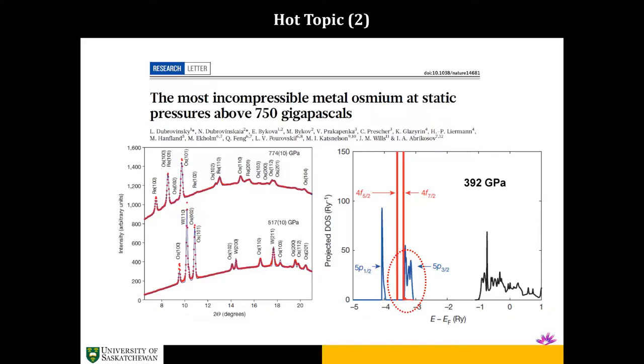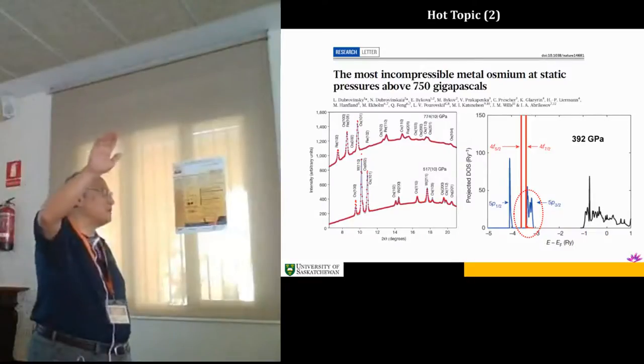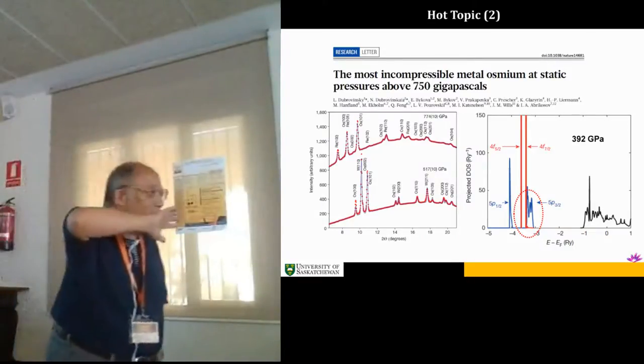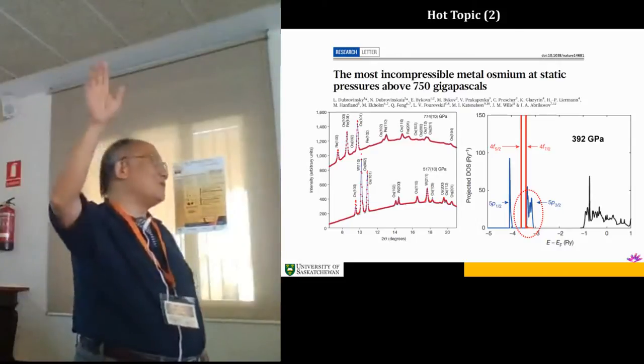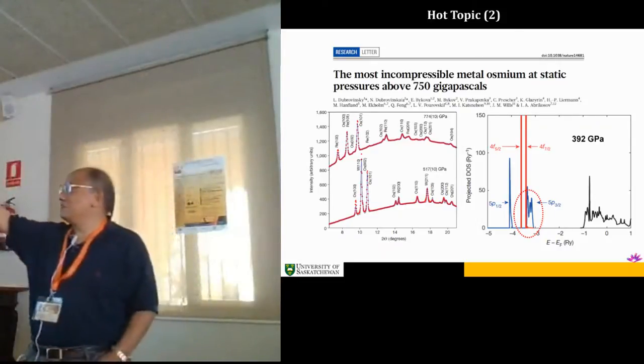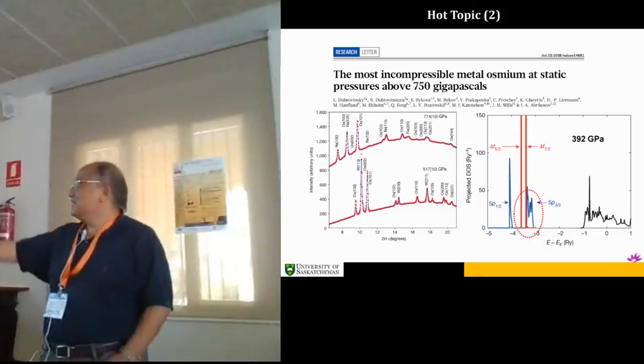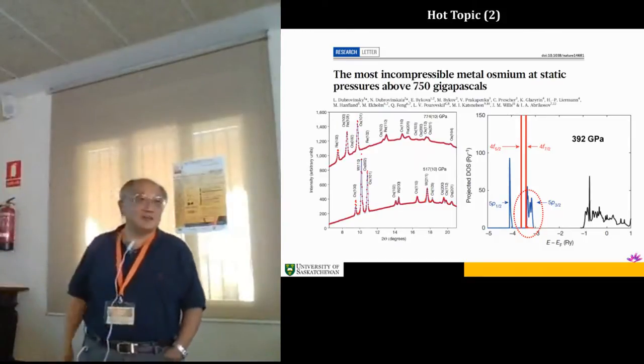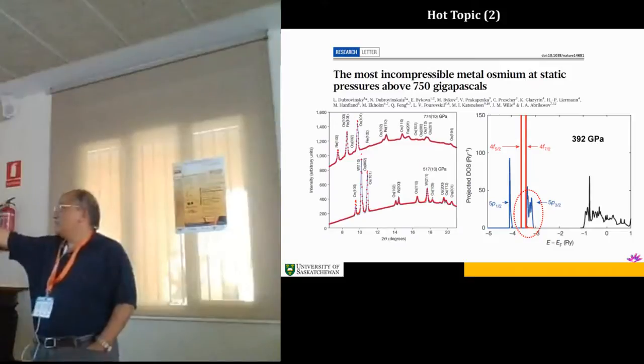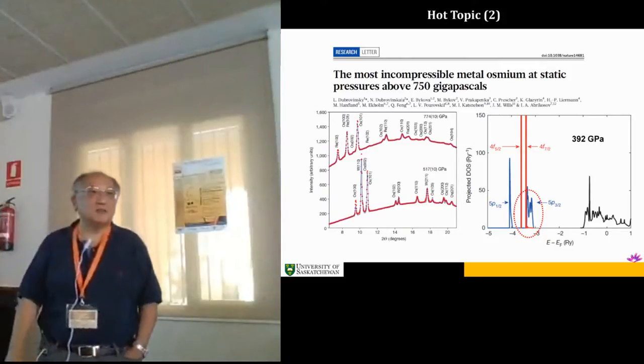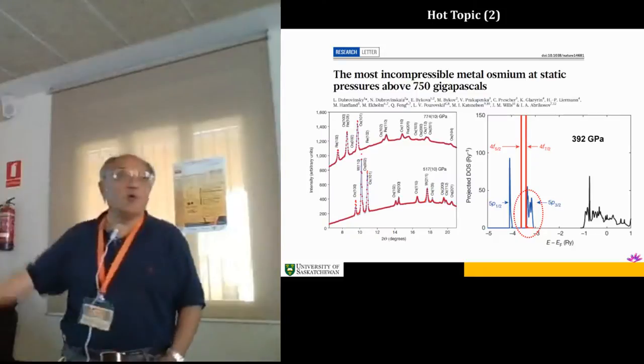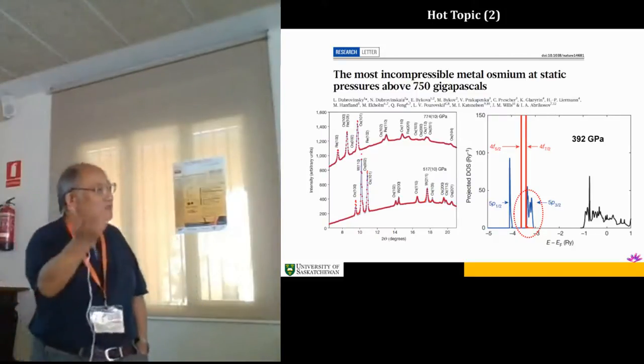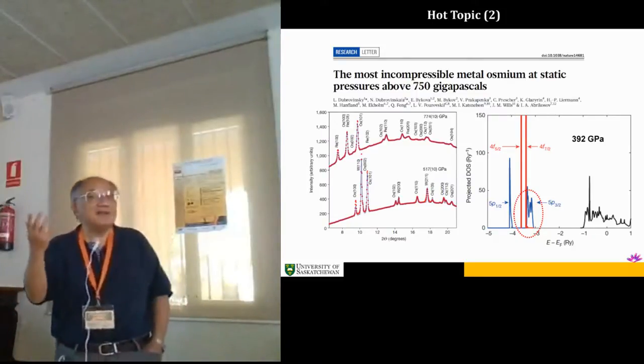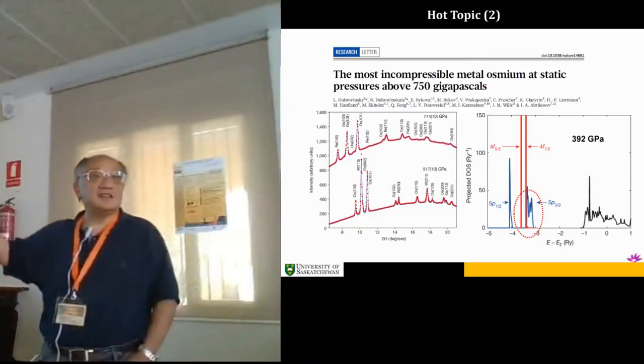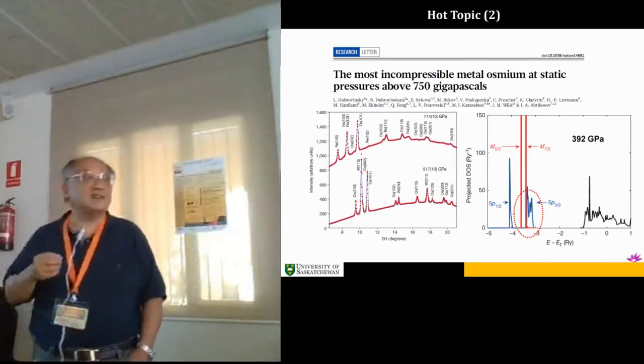Osmium, in fact, Hafner published a PRL many years ago. It's one of the compounds you compress to 100 GPa. No medium, it doesn't broaden at all. But it carries on to 750 GPa, all right? And that's actually a couple of phase transitions. I don't want to go through it. At that pressure, exceeding 400 GPa, they think actually the cores participate in some sort of interaction. You can call it bonding, but it's some sort of interaction. And that's apparently the first evidence of something happening.